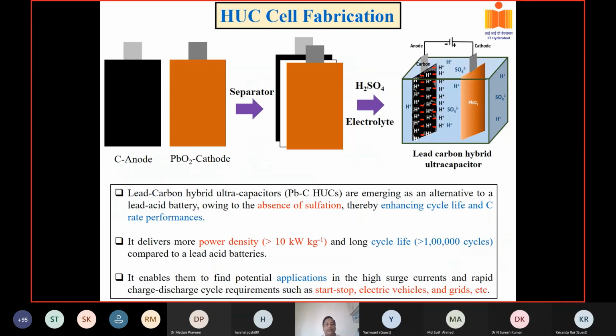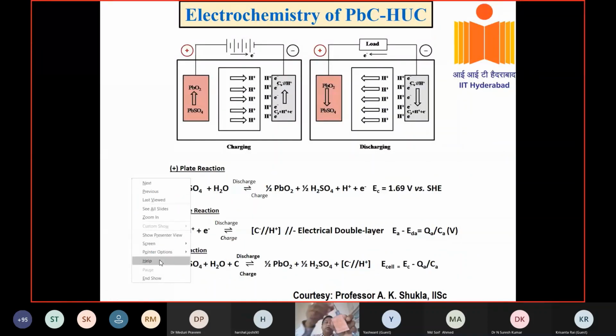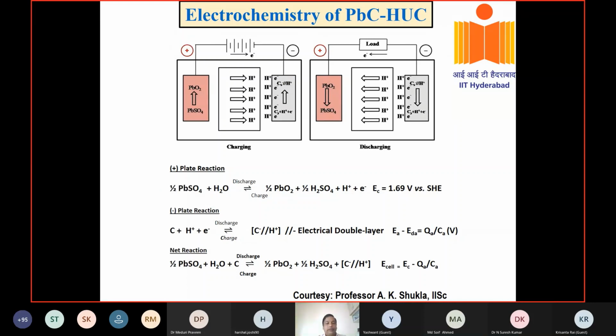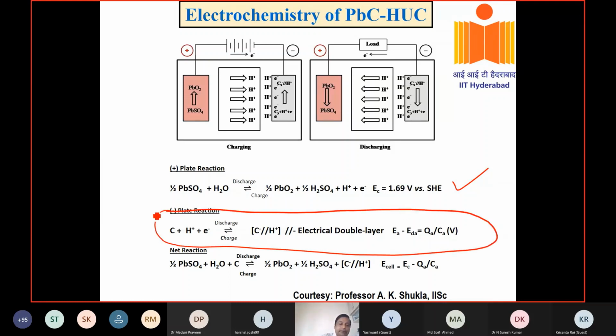So let's talk about lead carbon ultra capacitors. You have lead oxide cathode and carbon anode. But as you see here, we have a lot of mass in the cathode, so the anode needs to be optimized. Carbon electrode may not have that much mass, so this has to be done in a different way. The same way doesn't work. The lead electrode should be very, very thin. This is the same as your lead-acid battery electrode reaction, PbSO4 to PbO2, and the carbon has hydrogen adsorption on the surface of the double layer. That electrode interface adsorption gives around 2 volts, a little less than the lead-acid battery voltage, but it works very well.